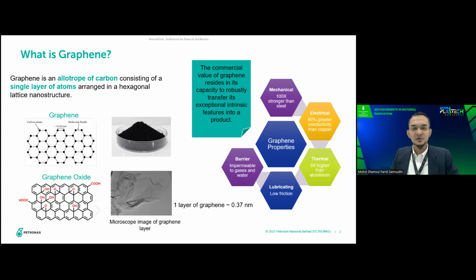Graphene, as we know, is a carbon-based material. As you can see here in terms of color, it is the same as carbon black materials. But the beauty of graphene is in its structure. Graphene, theoretically, we normally explain as a single layer of carbon atoms arranged in a hexagonal structure. And from this flake type of structure, or very thin sheet structure, it can be categorized into two types of product. The first one, we call graphene, where the purity of carbon is more than 98%. And the other one, we call graphene oxide, where the carbon structure has a few functional groups: hydroxyl, oxygen, and also carboxylic.